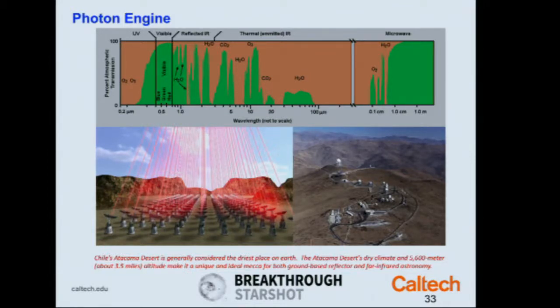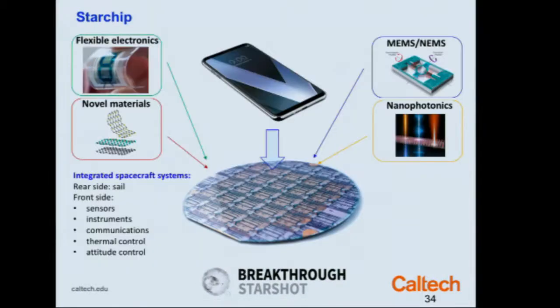And you'll notice here in the 1 to 1.5 micron region, there's a pretty good transmission window through the atmosphere. Obviously, there will be scattering and refractive index distortion. And in order to compensate for that, this has already been demonstrated by the Air Force: one puts a beacon in orbit that takes off a portion of the light beam and uses it as a reference to determine the refractive index effects of the atmosphere.